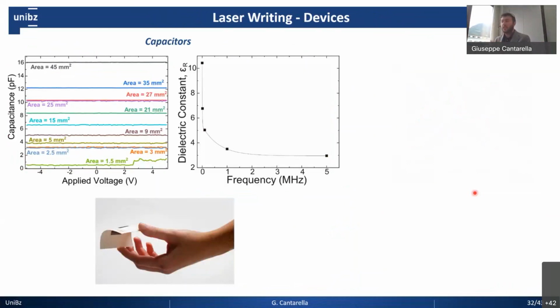So considering that we could have, for example, as I said before, conductive lines, the first device that came up to our mind was capacitors. So why don't we try to realize parallel plate capacitors, burning the top and the bottom surface of the paper? And that's what we got here. So we got capacitances that are in the picofarad regime, according clearly to the area, and the dielectric constant of the paper, which is in the order of 2.4, 2.5, as expected from the state of the art.